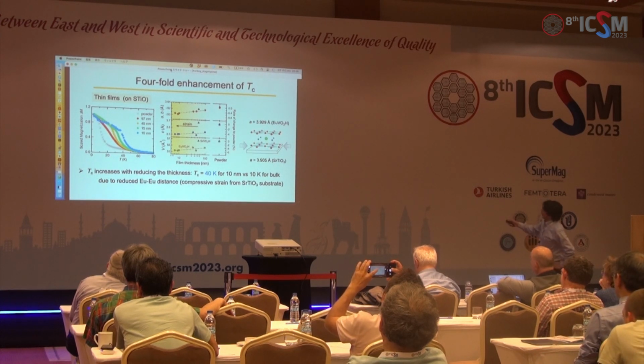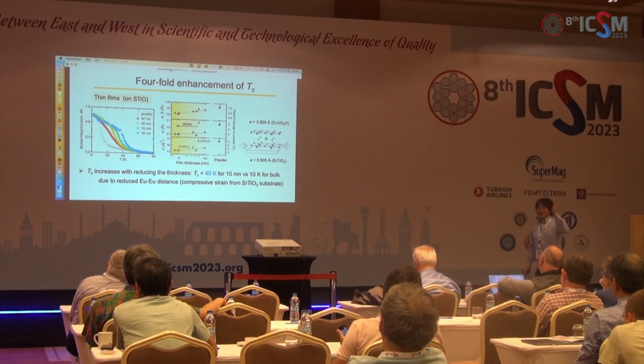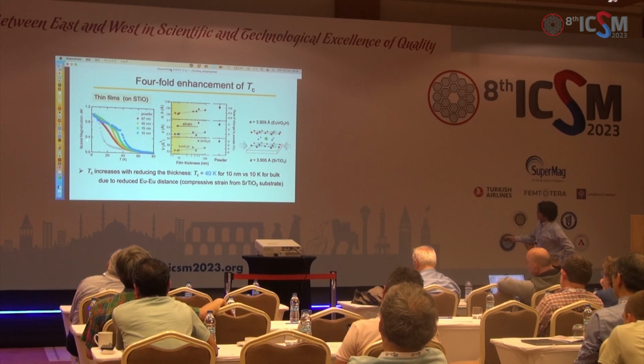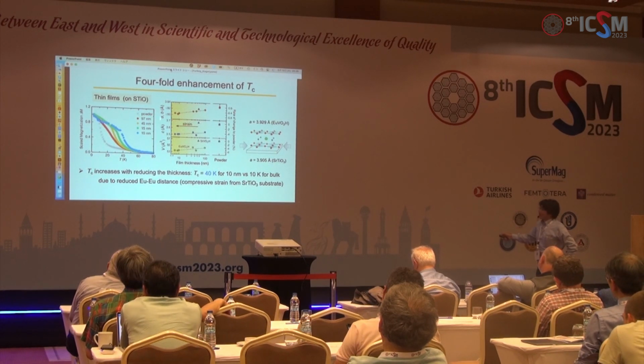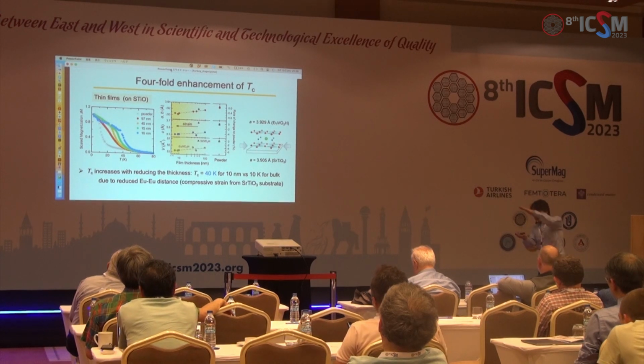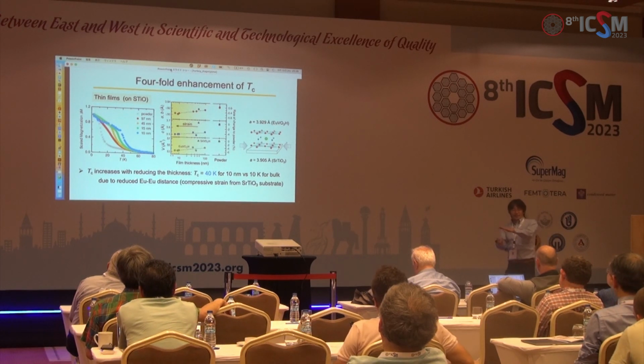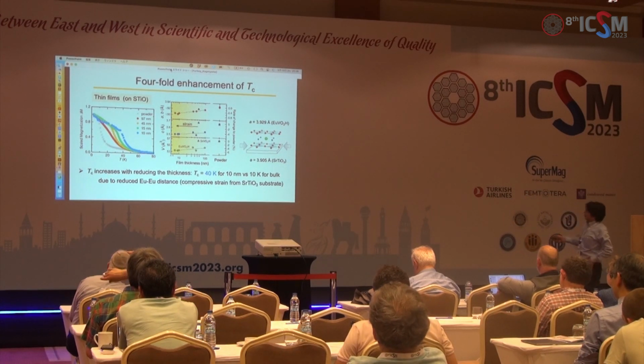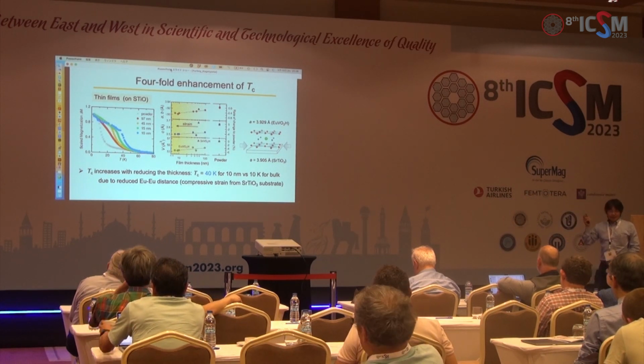One is the enhancement of TC. The powder sample TC is 10 Kelvin, but when we use the thin film, the TC is enhanced. Apparently, when we decrease the thin film thickness, the TC is enhanced. So when you make the thin film thinner, then TC is enhanced. So this is one of the observations from the thin film samples.